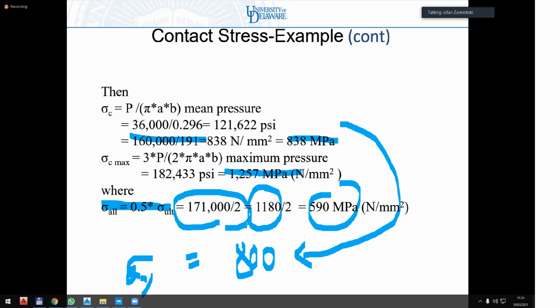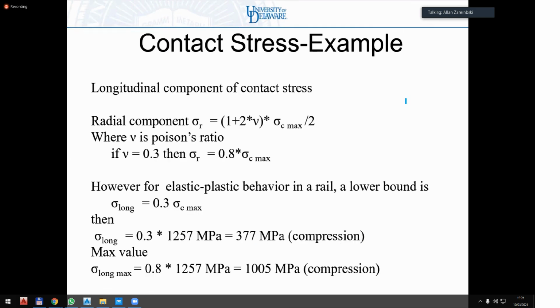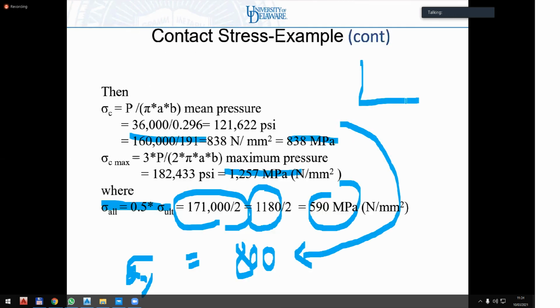So you can see that the contact stress zone we're working in is usually already at the edge of the elastic into the plastic zone, which means I'm potentially subject to plastic deformation in my rail. This is, of course, the vertical stress.